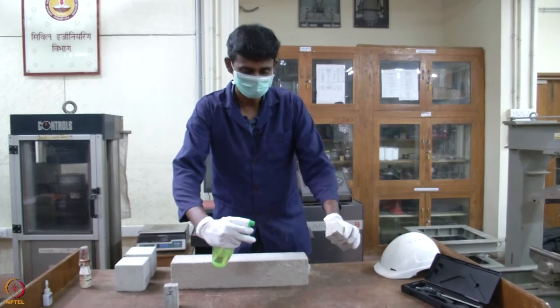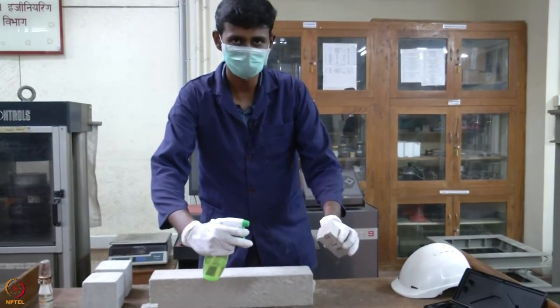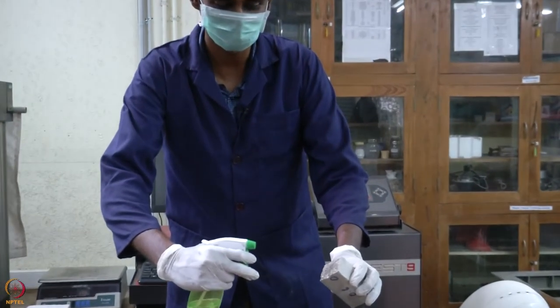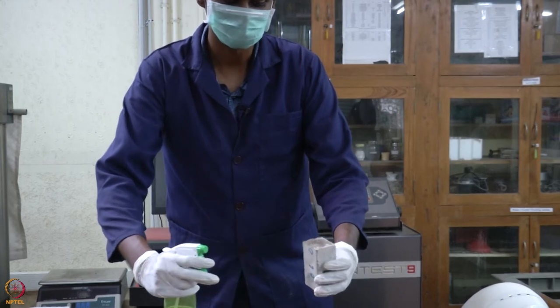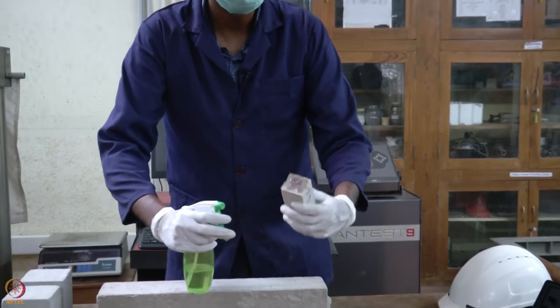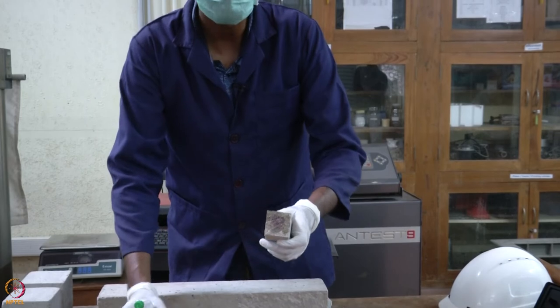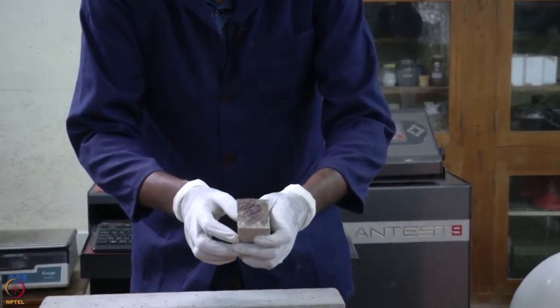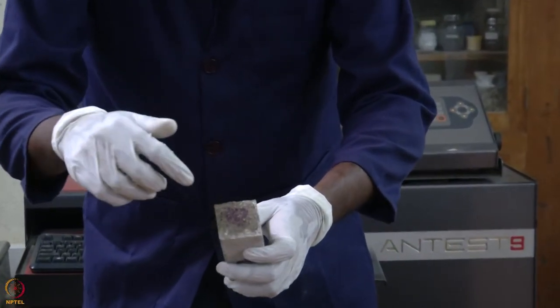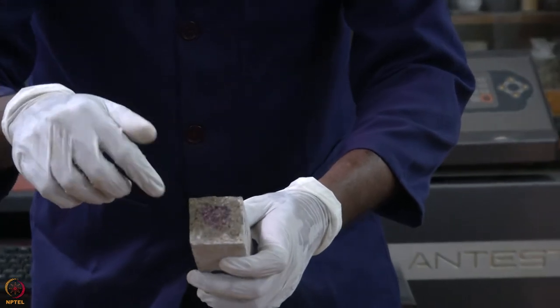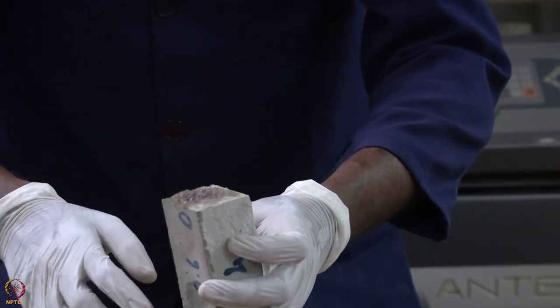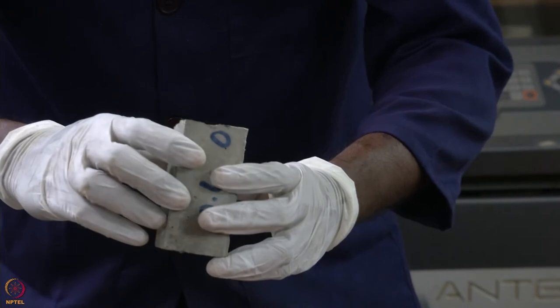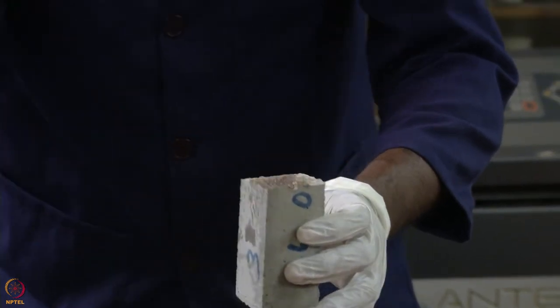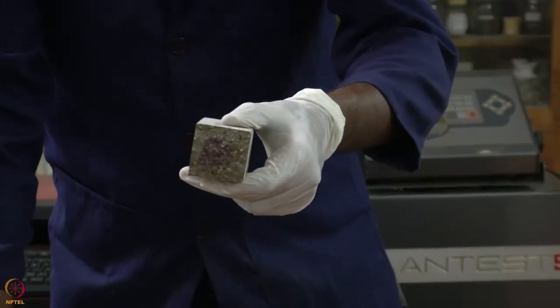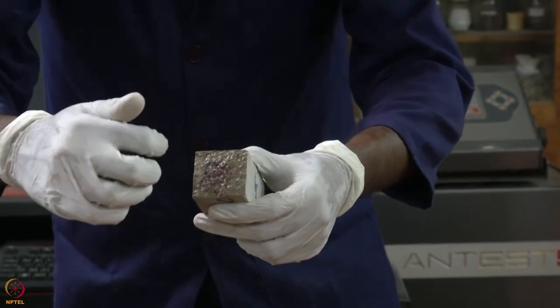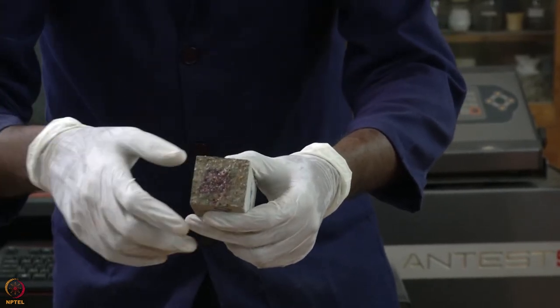That should be kept slightly away from the fractured surface, and then we should spray it over the broken surfaces. So you could see the carbonated portions are staying colorless, and the non-carbonated portion will be in pink color as expected. So this is how we could find it: the colorless zone will be the carbonated zone, and the center pink zone will be the non-carbonated zone.